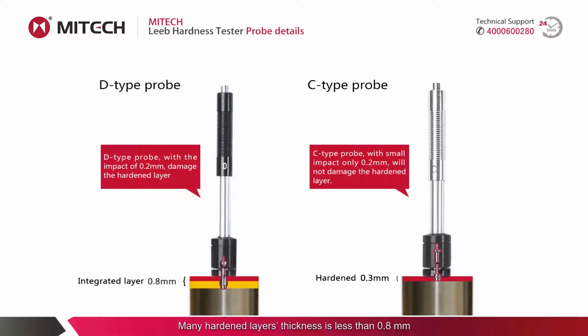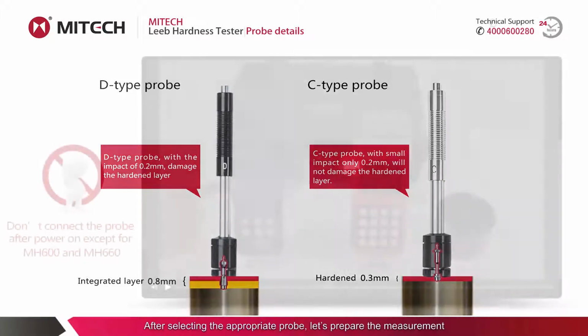Many hardened layers' thickness is less than 0.8 mm, and the measured parts are the hardened and non-hardened layers. If the C-type probe is not selected correctly, we will not be able to get the hardness value of the hardened layer. After selecting the appropriate probe, let's prepare the measurement.